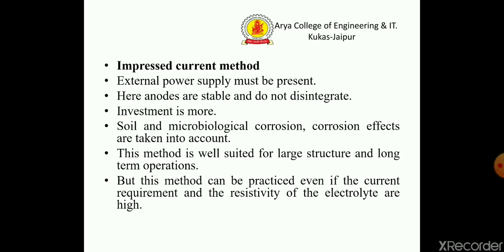In the impressed current method, an external power supply must be present; anodes are stable and don't disintegrate; investment is more; soil and microbiological corrosion effects are taken into account; this method is well suited for large structures and long-term operations; and it can be practiced even if the current requirement and resistivity of the electrolyte are high.